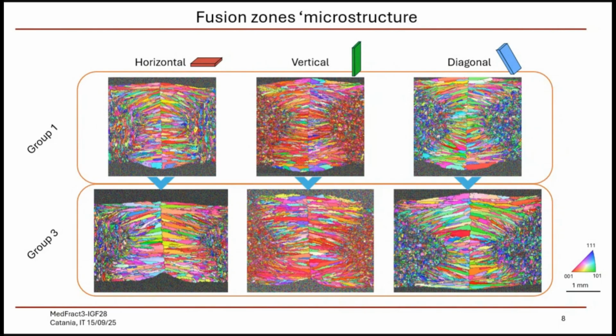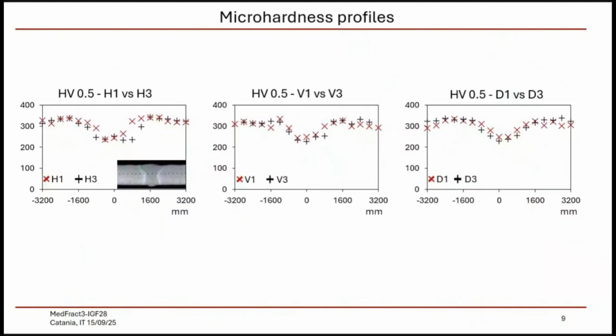So we have these elongated grains growing from the boundaries of the fusion zone towards the middle of it. But for example, you might know that when the welding speed is too slow, you might have the formation of equiaxed grains in the middle of the fusion zone, but we don't see it. So it means that within this range of process parameters investigated, we don't induce strong differences in the fusion zone microstructure, and not even in the microhardness.